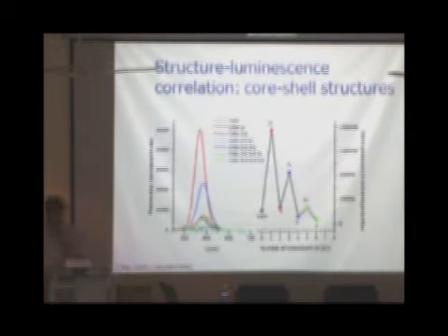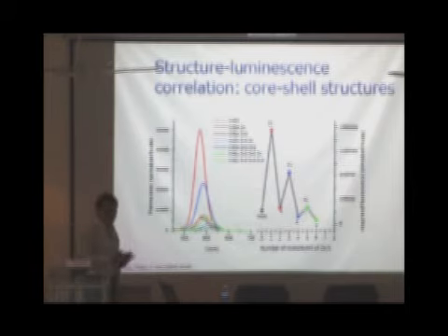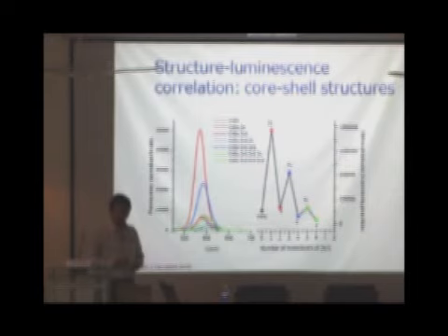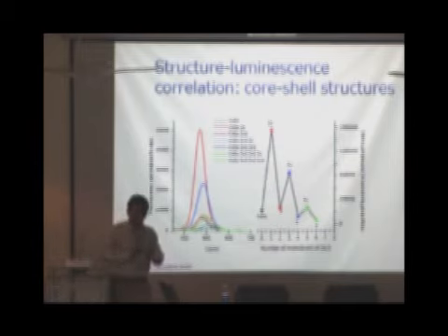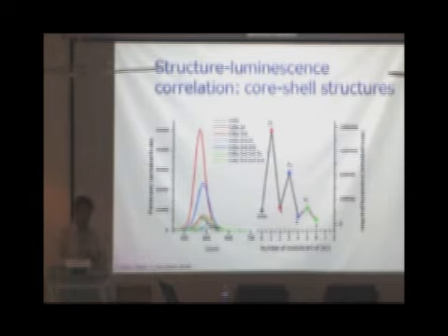So this one I'm going to discuss about light emitting materials. This is a cadmium selenide core coated with a zinc sulfide shell. A very interesting thing was that it really depends on the kind of surface atoms that you have. Surface plays such an important role. So if I coat one monolayer of zinc, the fluorescence intensity shoots up. But then if I coat a second monolayer of sulfur on top, intensity comes down. So zinc is very crucial. Although the coating is zinc sulfide, the type 1 structure that we are forming is because of zinc sulfide, but sulfur on the surface brings it down.